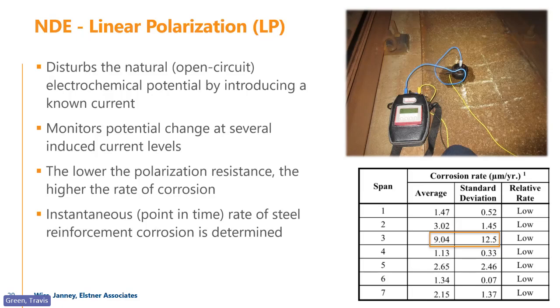On this particular structure, the corrosion rates are actually quite low. Some of that might be due to it was dry in that period, that time we were doing measurements. That does have an impact, and at the time it was really cold, and so that also can affect these measurements.